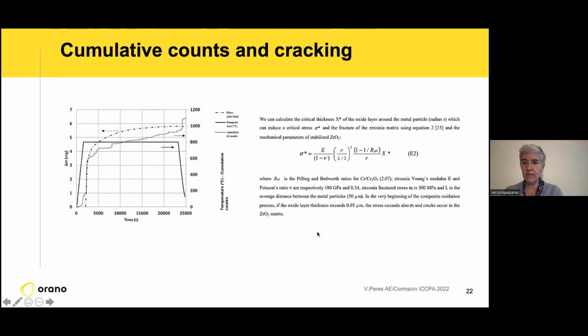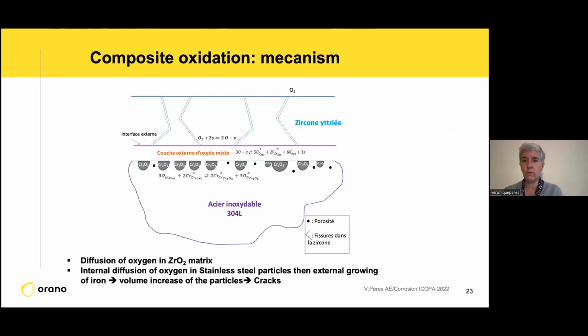And this layer is very, very thin, around 0.05 microns. And if this layer appears inside the sample, you can hear some noise. This is another case where we can follow the cracks in the system. So this is the mechanism.